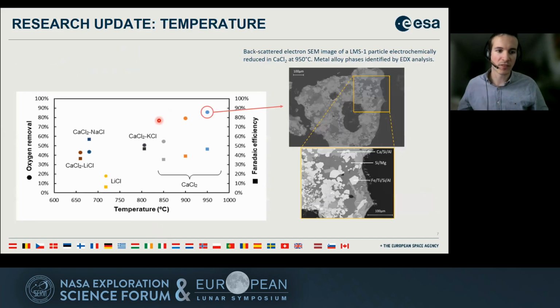So regarding the material aspect, what we actually recover. When you have close to full reduction, you can clearly distinguish some different phases in a grain of material extracted. So it's not usual alloys that you will get. It could be, for instance, calcium, silicon, aluminum, or silicon, magnesium, or iron, titanium, silicon, aluminum. So now we are also investigating what we could do with this powder. Either we could try to oxidize it again and make maybe some metal fuel, or try to 3D print it. So these are still open, and that's another branch of research.